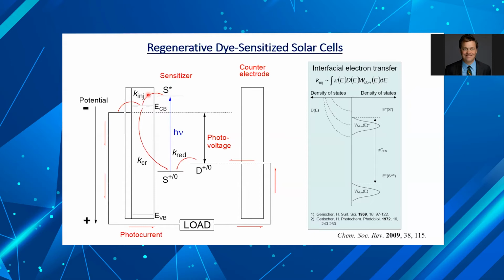Because the dye is absorbing light at longer wavelengths than the semiconductor, we often say it sensitized the semiconductor to longer wavelengths of light, and therefore dye and sensitizer, those terms can become synonymous. We sometimes just call the dyes sensitizers. Now, once you transfer an electron into the semiconductor, you create an oxidized dye. And in a regenerative solar cell, a redox mediator, typically iodide, regenerates that ground state dye so that the sensitizer can absorb another photon and inject it.